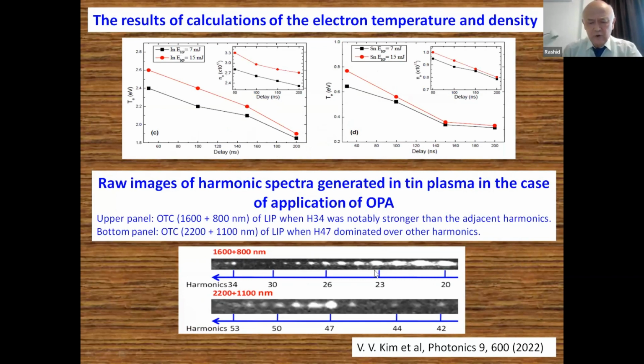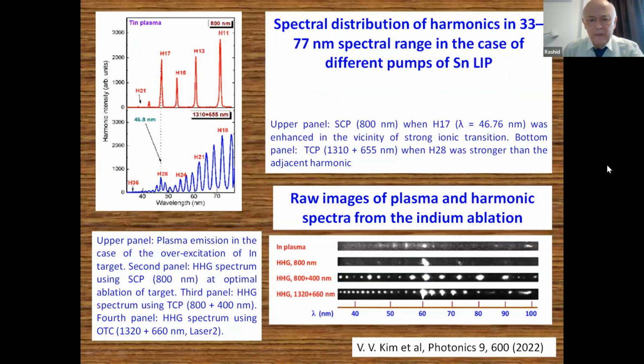and obtained at those optimal conditions the high-order harmonic generation. Particularly in the case of tin, when using 1600 nanometer radiation, we observed an enhanced single harmonic in the range of the 34th harmonic of 1600 nanometers. Similarly, when we used 2200 nanometer radiation, we observed the same process, when the strong 47th harmonic became much stronger than the low-order harmonics, which is an unusual process for high-order harmonic generation. The same we observed in the case of the indium plasma. Here I show an image of the plasma spectrum, with generation of a single harmonic in the case of 800 nanometers in indium plasma.